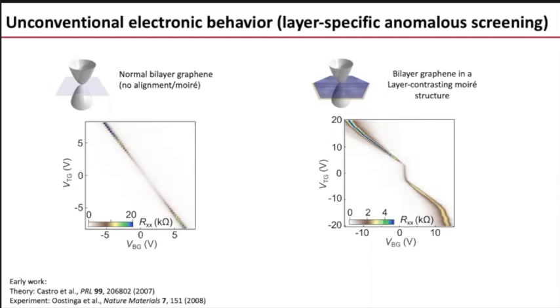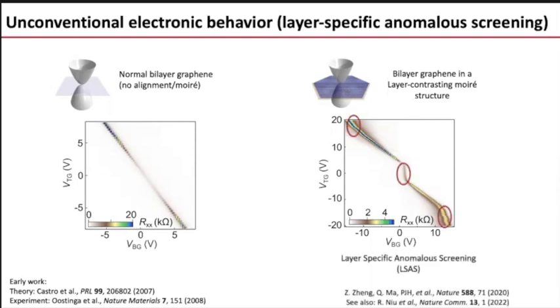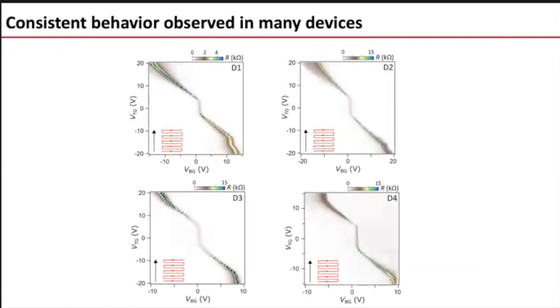But then we extended the range of the top gate and we saw that it actually was working. It was only in this middle region that it appeared not to be working, okay? Now, gate not working is not very fancy, so we call this the layer-specific anomalous screening, which happens in this region, and these regions, okay? We published this a few years ago. It has been reproduced by other groups. Now, at the beginning, we were very puzzled, and we thought maybe indeed the gate is not working, and there are some charge traps or some such thing, who knows, right? But then you do this, and you start seeing it in many and many devices, to the point that now we can actually engineer it to make sure it happens, and so on. So we know that it's not just some gate not working stuff, okay?